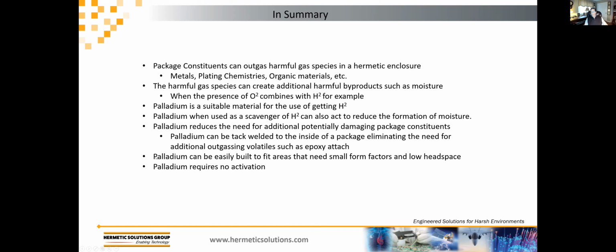The other neat thing about palladium is you can roll mill this material to varying thicknesses. It can be stamped into different sizes and form factors to fit in very low headspace areas. And lastly, palladium does not require any activation.